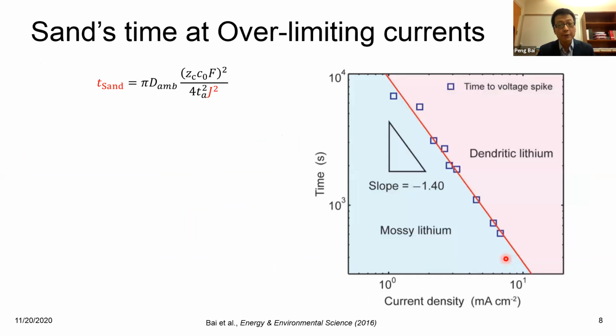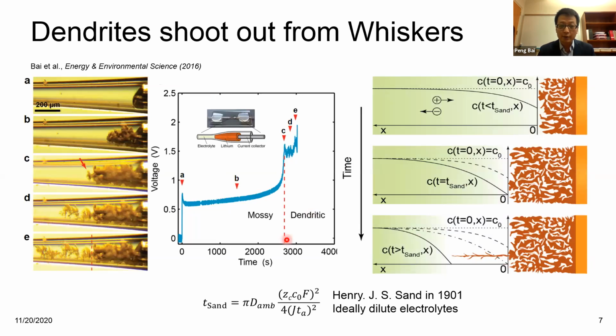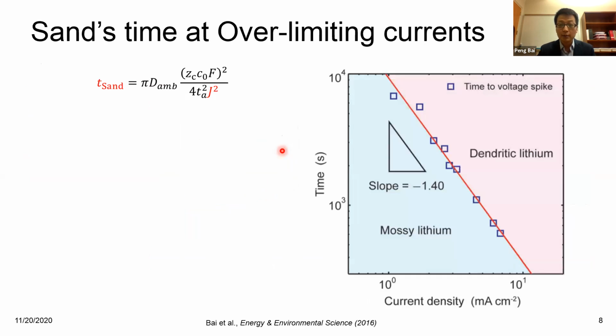So here, if we read the time when we see this transition of growth, the dendrite initiation and the voltage spike, we can vary the current density to find a series of dots. And just as the Sand time formula predicted, it follows a power law, right? So on this logarithm plot, it falls on a straight slope. What I didn't mention is that there is one premise you must meet, which is that you need to use a high current.